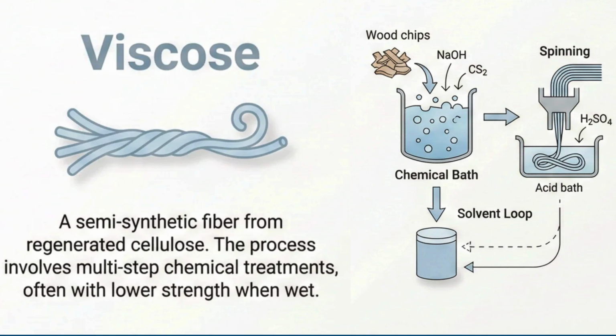Manufactured using the sodium hydroxide carbon disulfide viscose process, it is valued for its exceptional softness, silk-like drape, high moisture absorbency, and excellent dyeability. However, its relatively low wet strength and dimensional stability limit its durability during repeated laundering. Furthermore, the viscose process is the most chemically intensive among rayon manufacturing methods, requiring careful recovery of carbon disulfide and extensive wastewater treatment to reduce environmental impacts.